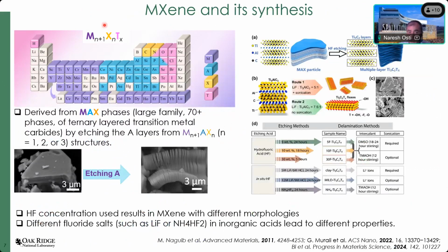Now, what are MXenes? I'd like to briefly introduce MXenes as well. MXenes are two-dimensional transition metal carbides or carbonitrides represented by this general formula. Those materials are synthesized from the MAX phases, where M is the transition metal, A is a group 13-14 element, and X is carbon or nitrogen or carbon-nitrogen together. When you selectively take the aluminum layer out of these MAX phases by etching, you end up with the MXene structure, which is shown here in the SEM images. Depending upon the different type of etchant, whether you use hydrofluoric acid of certain concentration or you produce the hydrofluoric acid in situ, and depending upon the nature of the agent that you use, you end up with MXenes with different morphology and different properties.